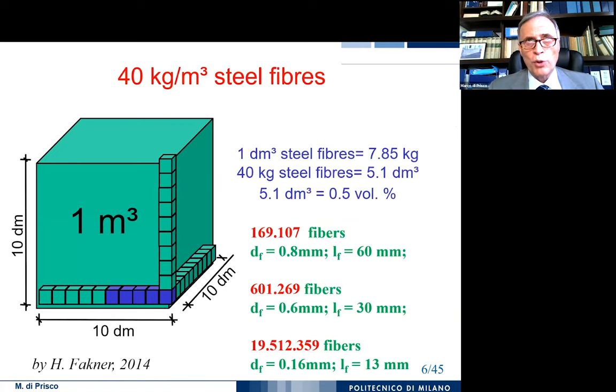There is another concept which is important. We are speaking about random fibers. So if we have, for instance, a cubic decimeter of concrete with a mix of only 40 kilograms of steel fibers, depending on the diameter and on the length of the fiber, we could have very important numbers, passing from around 169,000 fibers for the largest fibers, what we name macrofibers, to more than 19 million if we have what we name microfibers, so fibers with only a diameter of 160 microns.